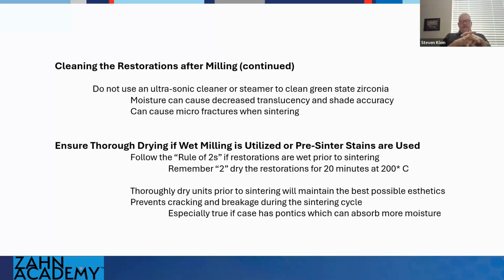If you do, and you have them wet, you have wet milled, so that would be the only time that I would tell you to use an ultrasonic cleaner to get that dust off of them. And you'll see it as soon as you place the crown into the jar or whatever container you're using in the ultrasonic cleaner, you see a little cloud of white dust surround that crown. It's shedding and getting rid of all that. Here's the key. When you take it out, you want to make sure that you get it very thoroughly dry, and I mean bone dry.